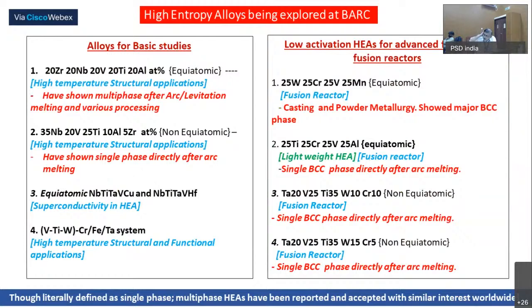And based on that, when we were doing this study, we found that the composition can actually be tweaked, and we can find other compositions which can show a single phase structure. That structure is shown in the next series, where one of the phases in the study of the first lab, when we did it, we found this phase was showing a single phase, and that was 35 niobium, 20 vanadium, 25 titanium alloy systems. In addition, we were trying to explore superconductivity.